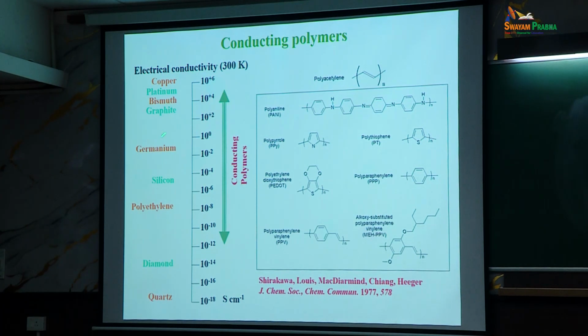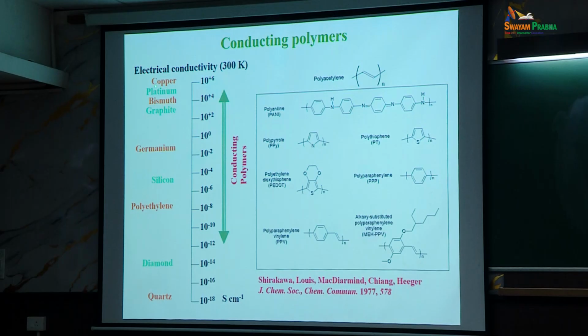So this is what I told you earlier, this sort of rough chart of conductivities of various materials. Quartz is one of the best insulators, very, very low conductivity. This is in units called Siemens per centimeter or ohm inverse centimeter. So 10 power minus 18, extremely small. But copper, platinum and so on are 10 power plus 6. And of course, conductivity is temperature dependent, so I'm quoting them around 300 Kelvin, room temperature. So you can see from copper to quartz, there is almost 24 orders of magnitude variation in the electrical conductivity. One of the very important, interesting properties that can change.